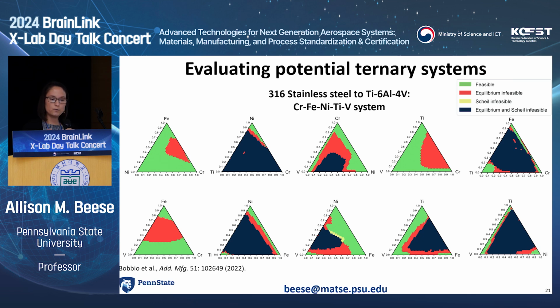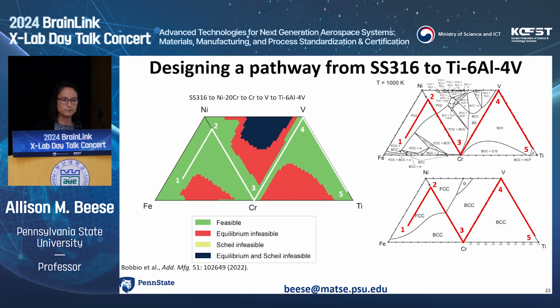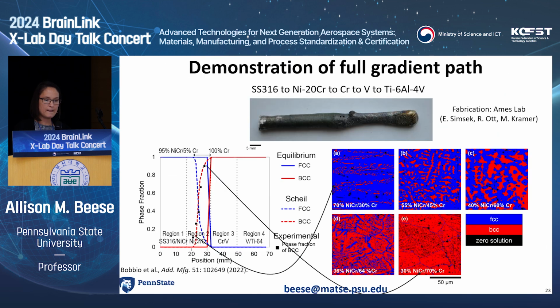And there's actually only one way that we can put those together like a puzzle to get from stainless steel to Ti-6-4, and that's shown here. So this tells us we could go from stainless steel to nickel chrome to vanadium to titanium, and equilibrium and Scheil predict that we will transition from FCC to BCC. So we're avoiding then the intermetallic phase formation by introducing lots of intermediate steps.